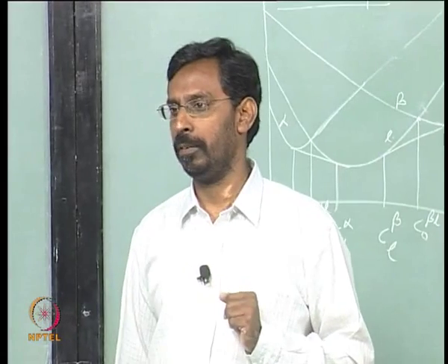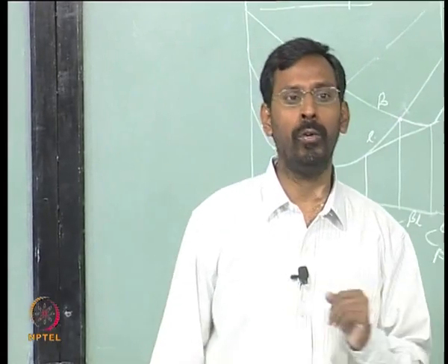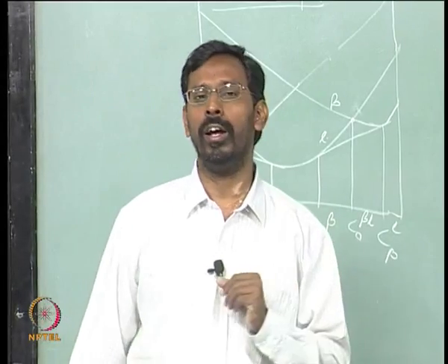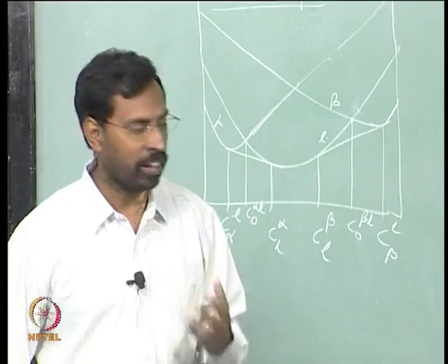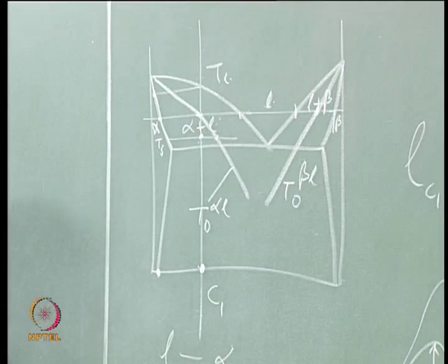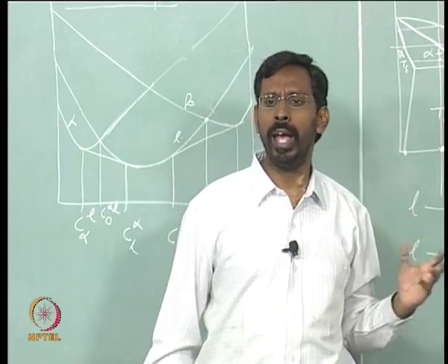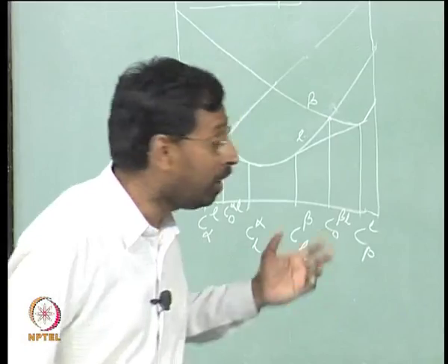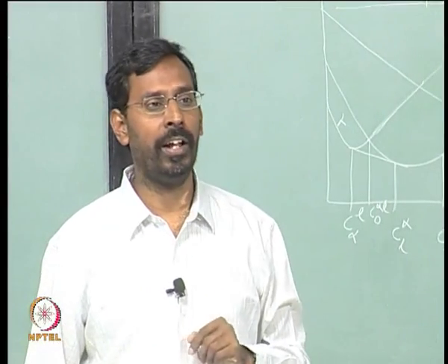that you can completely change the way solidification occurs. If you can really undercool an alloy below the T naught, you can have the solidification taking place in such a way that instead of a normal regular eutectic solidification, primary phase and eutectic mixture, you would simply have what is called a single phase partitionless solidified alpha.